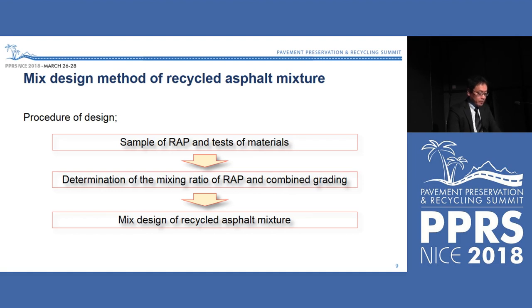First, RAP is collected and subjected to materials tests to determine whether it can be used as recycled aggregate. Then, the amount of rejuvenator or virgin binder and the mixing ratio of RAP are determined. In addition, the provisional blend asphalt content, which is the central value when conducting the Marshall stability test, is determined. Finally, for the mixture determined by the aforementioned conditions, the Marshall stability test is conducted in the same manner as a virgin asphalt mixture, and optimal asphalt content is determined.